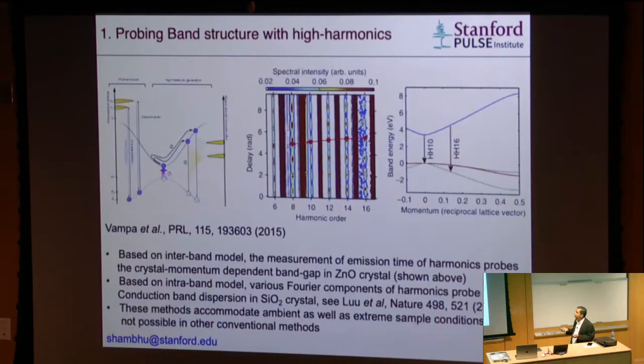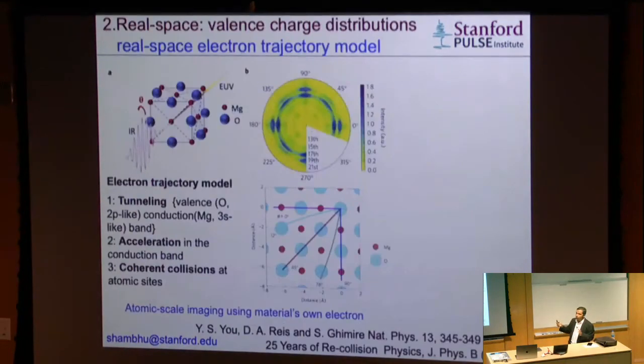So this is exactly what this group at Ottawa proposed and to some extent realized in the same zinc oxide crystal, by measuring the emission times of harmonics and reconstructing, at least to some level, the band structure of the source material. There is a similar really nice work from Leitenstorfer's group when they were at MPQ, where they took the channel 1, the Bloch oscillation channel, and they probed the conduction band of the crystal quartz. So those are the reciprocal space applications. Harmonics can probe, at least they have the strength of probing, the electronic band structure.